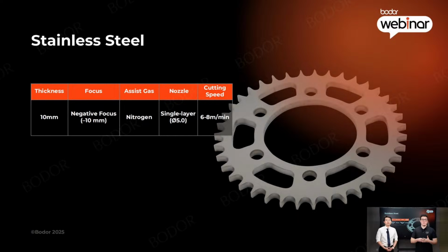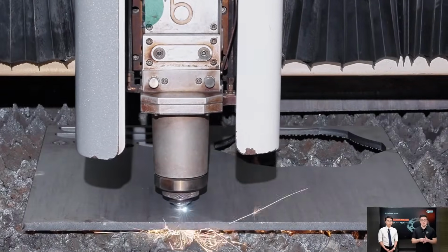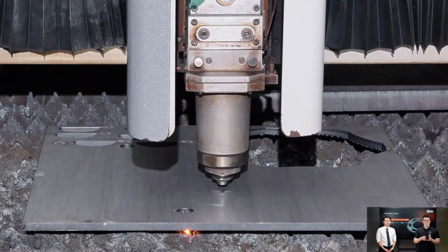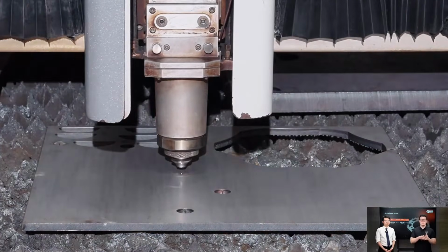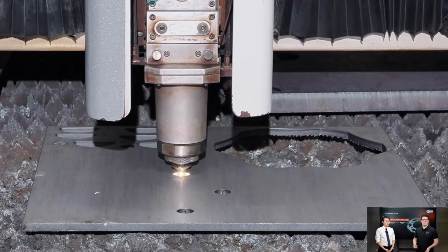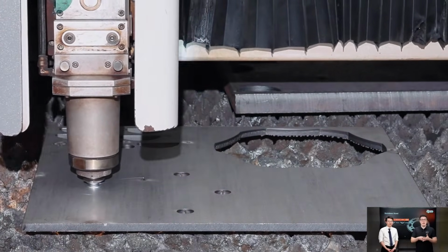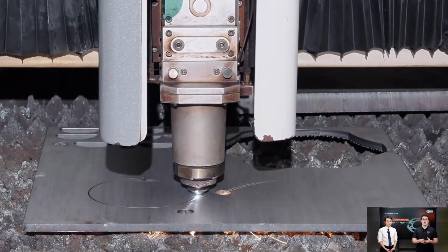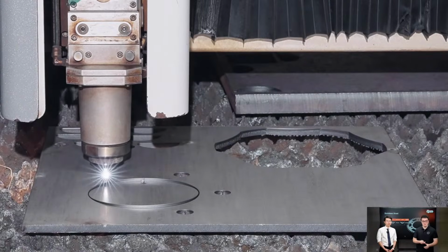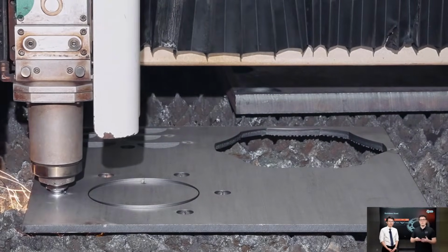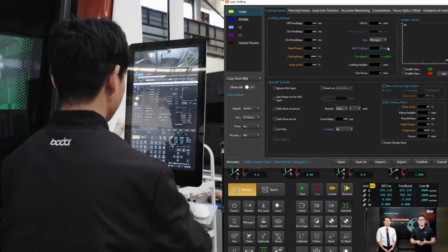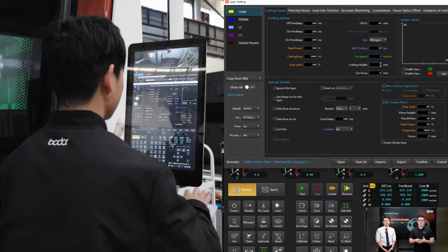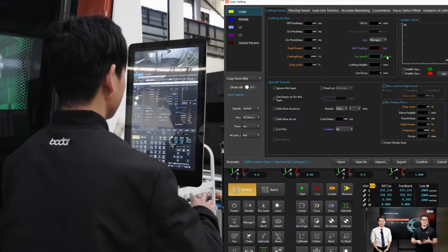Now it is time for stainless steel. I know many of you cut stainless every day, so this one is definitely for you. We are working with a 10 millimeter stainless steel sheet, and this time we are switching to nitrogen as the cutting gas. Why nitrogen? Because it keeps your edge clean, bright, and free from oxidation. No burn marks, no dark edges. For this cut, we are using a negative focus set to around -10, a single layer nozzle of roughly 5 millimeters in diameter, and nitrogen as the cutting gas.